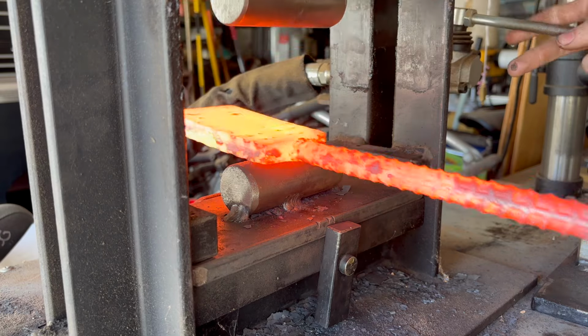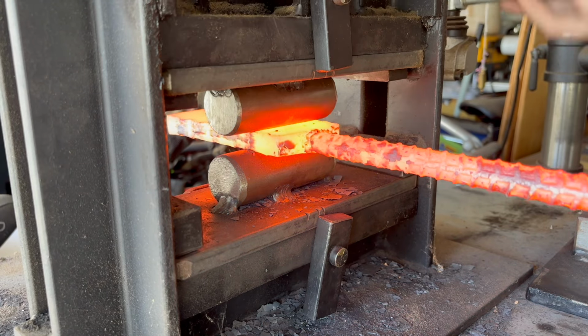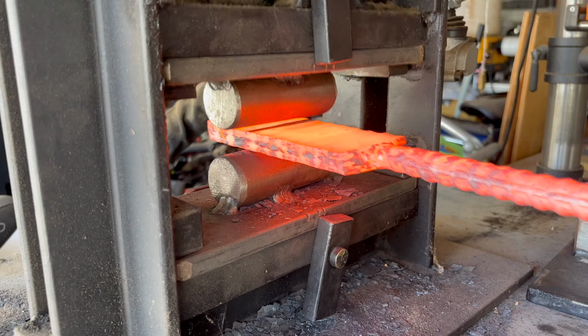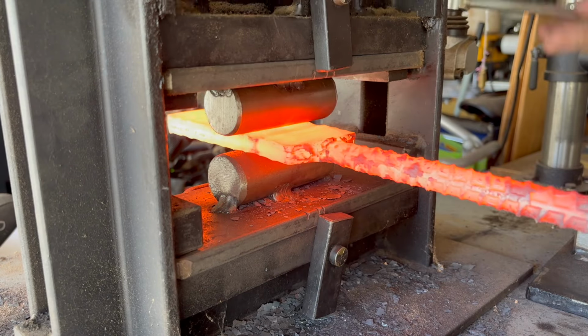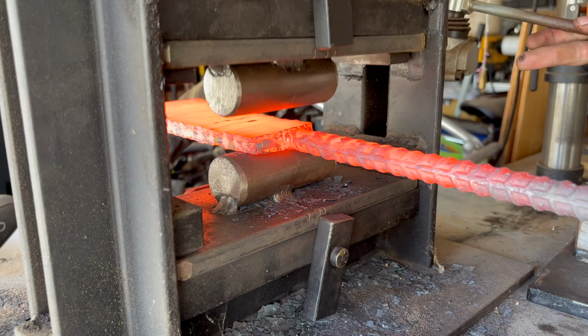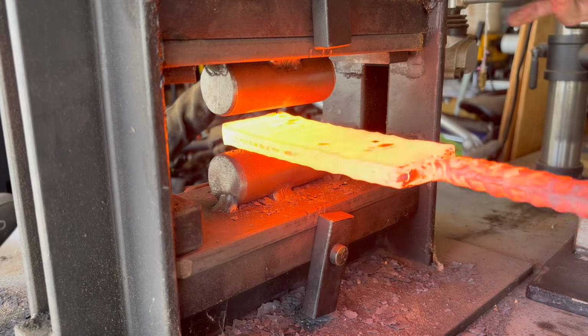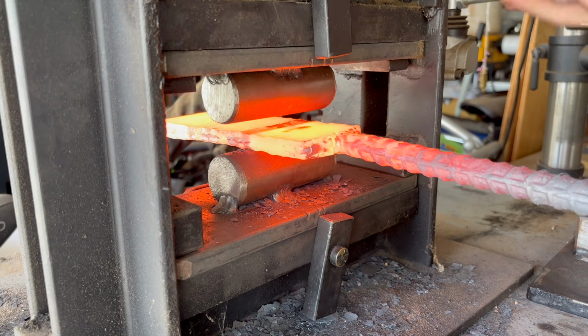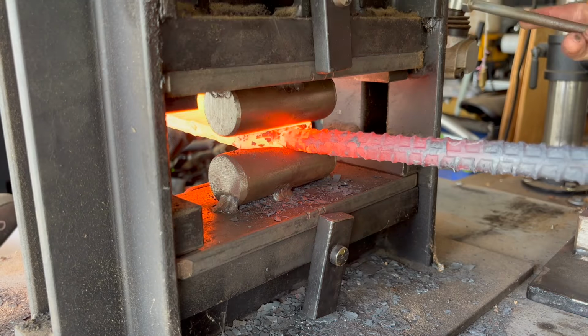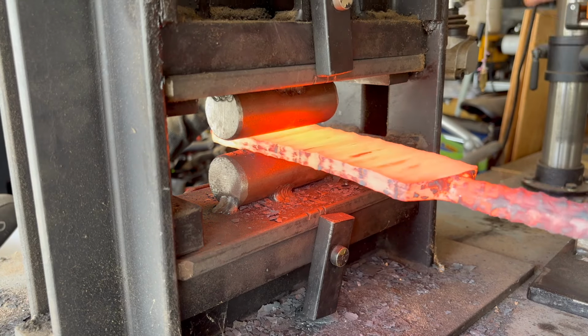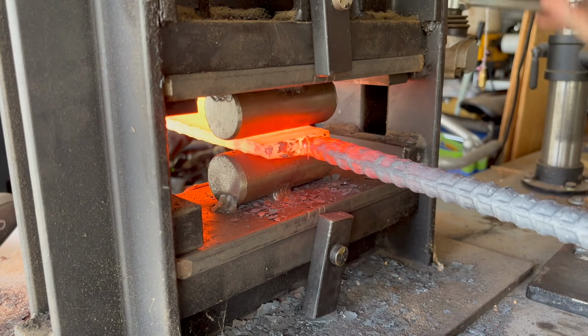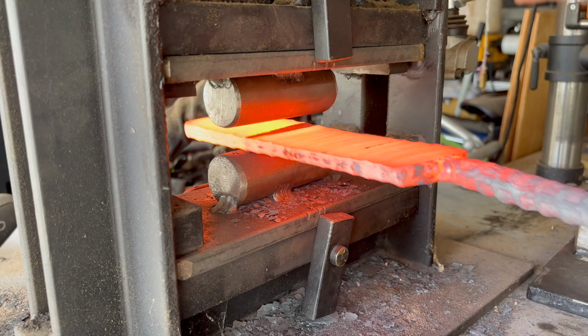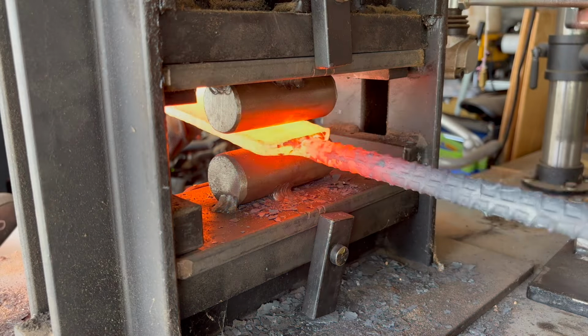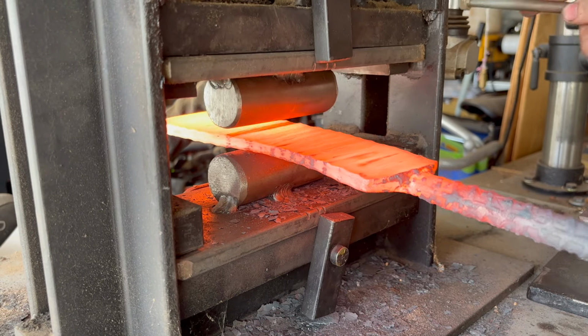Now, using the drawing dies, I'm still taking really short, light passes, and that's just so that it doesn't hurt the welds in any way. And I don't really want to be distorting the pattern at this point because it's still really thick. And the way I get the pattern, like the peaks and valleys, is when I'm starting to use the press to get the thickness of the blade that I want. I can squeeze with these drawing dies where I want the peaks and valleys to be, and that's how I kind of control the pattern.